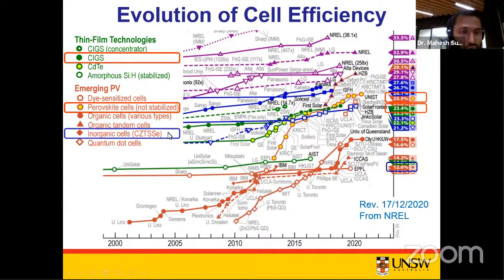So as an analogue to this chalcopyrite compound, that is CIGSSe, the kesterite CZTSSe compound has achieved a world record efficiency of around 12.6% in 2014, and the paper came online in 2015. The record efficiency has been achieved in less than 6 years, starting from 2008 by Professor Katagiri from Japan. However, this efficiency of 12.6% has been stagnant since 2014.